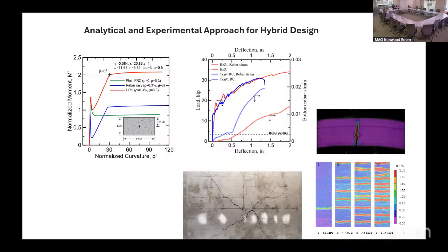So basically what we show is that I'm going to saturate this sample with cracks. It's not going to give up until all of these radial cracks form in that panel that I'm testing. It's not a single crack that easily grows. And those calculations basically take you to the figure on the left. The green line that you see